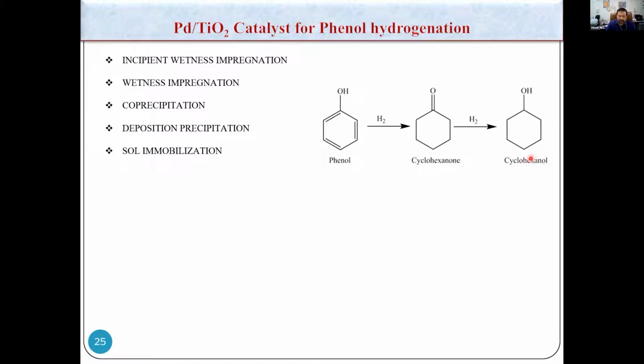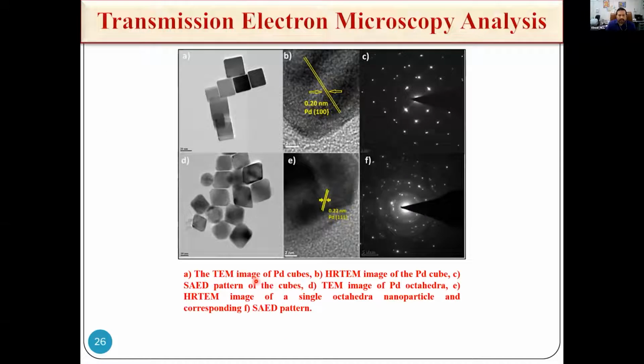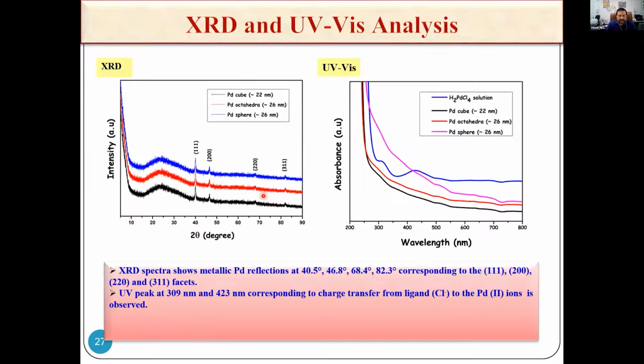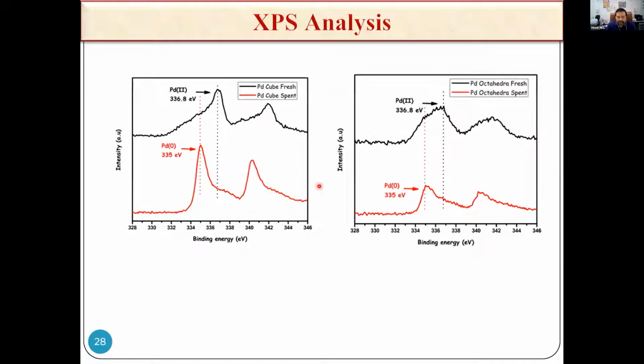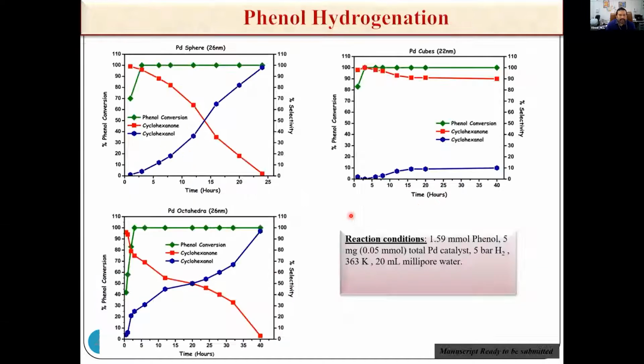So as I said, the reaction that we carried out is a phenol hydrogenation. It can produce cyclohexanone or cyclohexanol, depending upon what kind of catalyst you use, which transition metal you are using. And we have actually used palladium cube and octahedra supported on titania to look at this particular reaction. So these are palladium cubes, or the colloidal palladium nanocubes that have been made in the lab. Right, I will just skip all these things, and these are characterizations, which I again don't want to spend too much time on. This is the important part. Okay, so you take a palladium sphere, which is 26 nanometers, and you carry out phenol hydrogenation, and within 5 hours you reach 100% conversion.